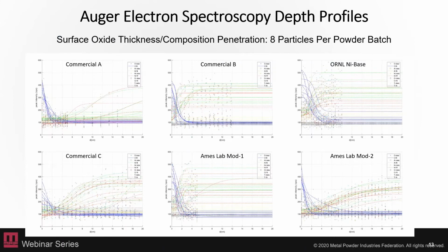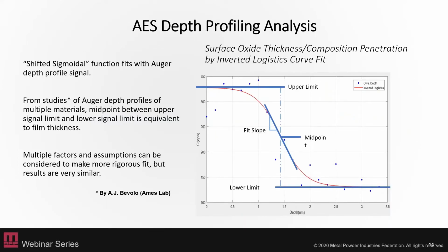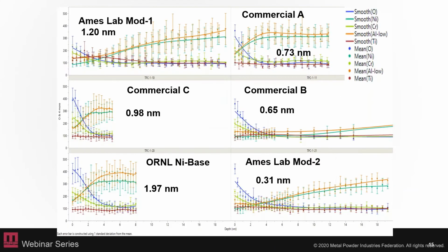So here, again, are different commercial powders as well as some produced at Ames Laboratory. Same nominal composition, but a wide variation in the surface oxide thickness and composition as a function of penetration of the material. The X scale bar there is in nanometers, and the intensity level is just based upon the intensity of the counts. The blue curves are your oxygen data, and then these are nickel, aluminum, chrome, and titanium curves for elemental compositions, increasing in the green and the blue colors. These powder particles were measured, 8 powder particles per batch, to get some statistics behind these measurements. And then these profiles were analyzed using a sigmoidal function fit to get a midpoint, and then analyzed with some error bars, obviously, too.